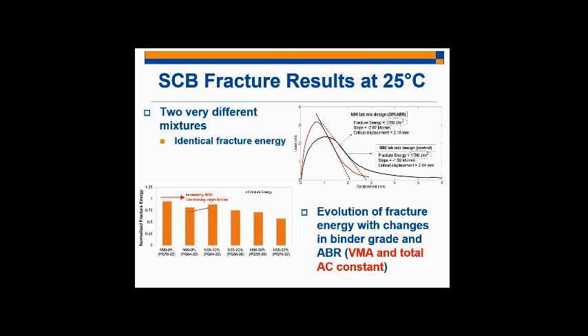So essentially what's happening is a deterioration of the mixture as you take it more to the brittle end of the performance spectrum. And so as you're increasing the ABR, you are decreasing the virgin binder in the process. And VMA and total AC content were kept constant.